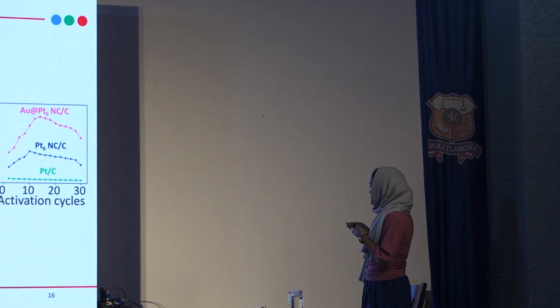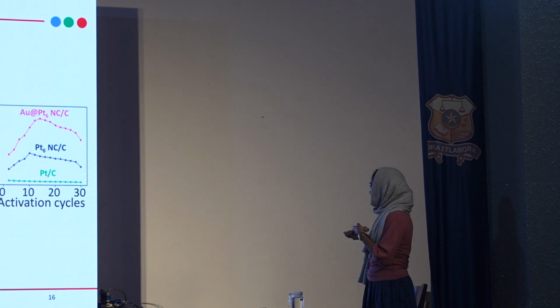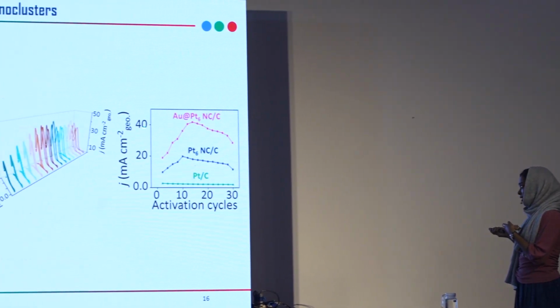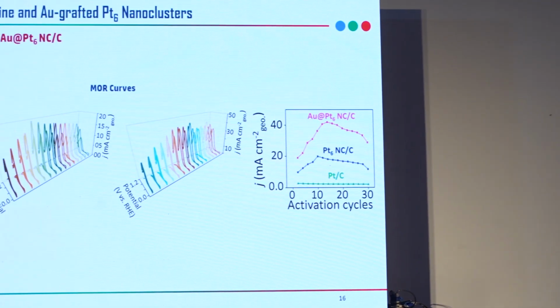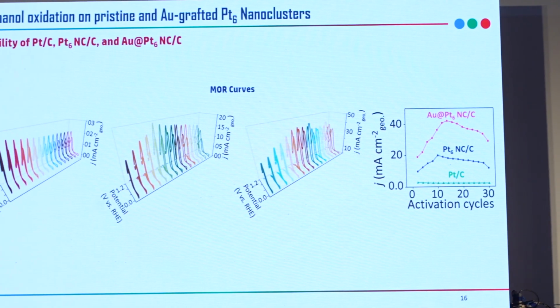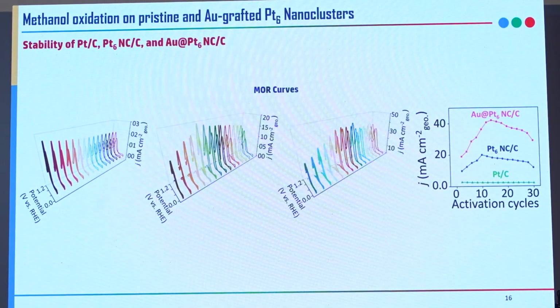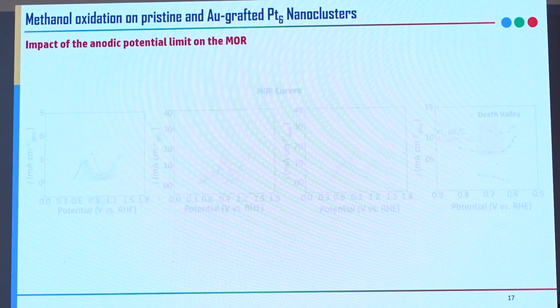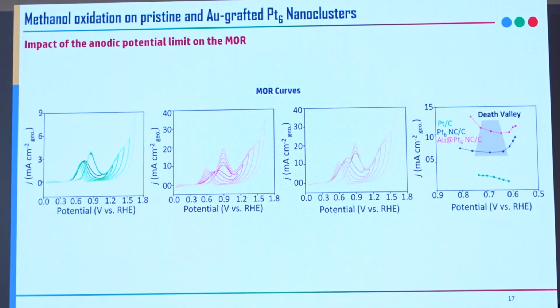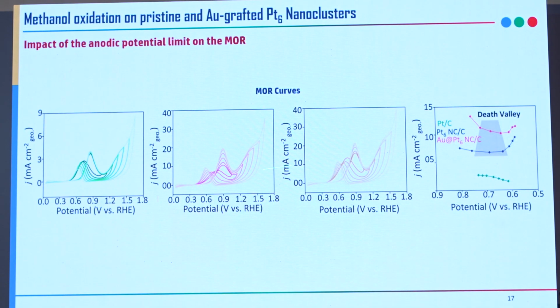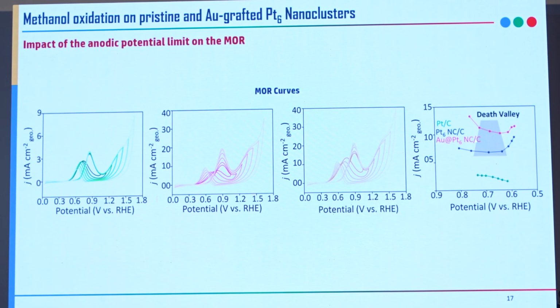And the stability also revealed both the Au decorated one and PT6 NC show higher stability in terms of recycling and reactivation. And for the impact of the anodic potential, the Pt/C has less stability when compared to the Au decorated one and PT6 nanoclusters.